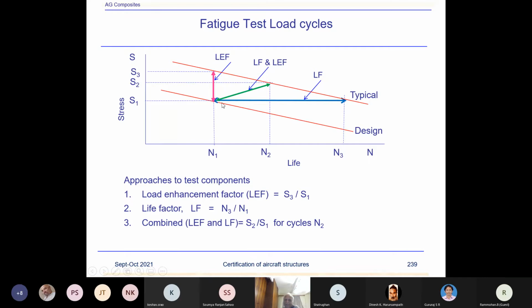And the load enhancement factor could be around 13 to 15%, depending upon the modes, and some calculations are done. So typically around 13 to 15%, or could be slightly higher, but you don't want to exceed too much because that will put the risk to the metallic structure failures. So this is a practice normally used for the composites.